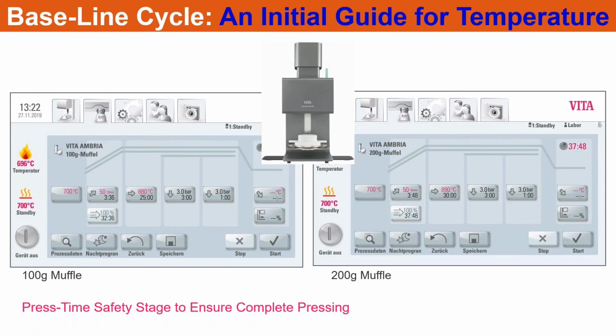So as far as the press process itself, the only high temperature we change is between 100 gram and 200 gram. We change the temperature by 10 degrees higher when we do a 200 gram. And then we also increase the heating time, the heat soak time in our press furnace.